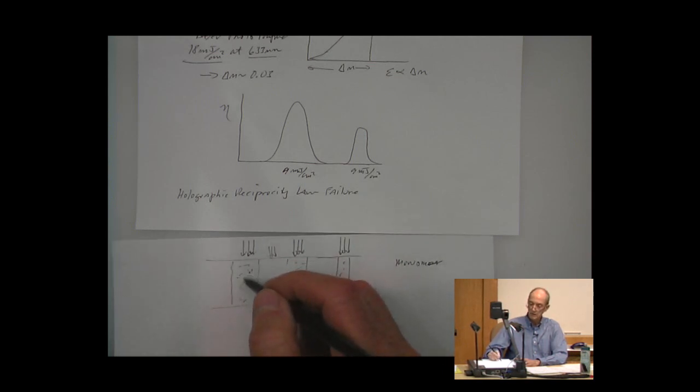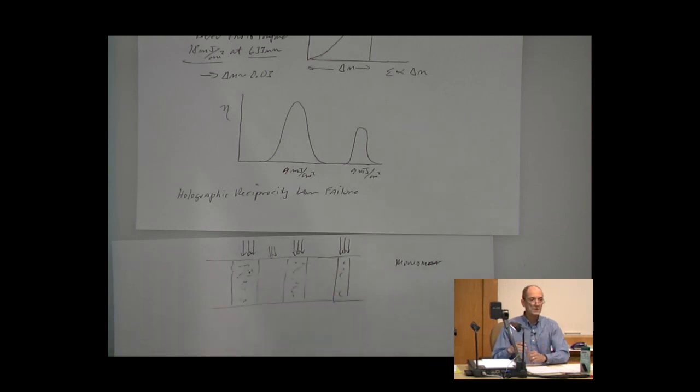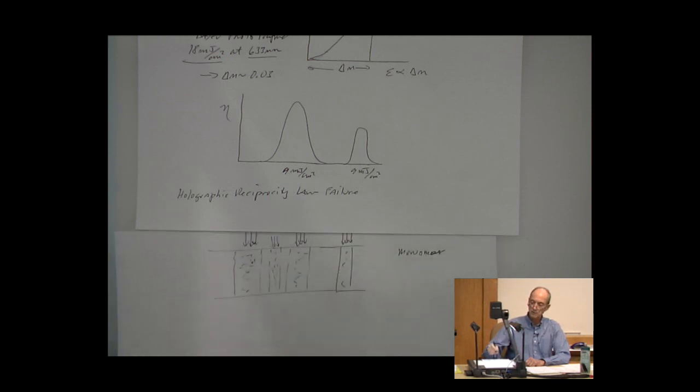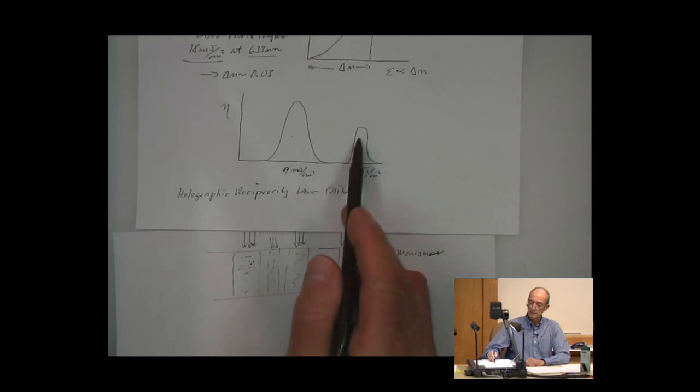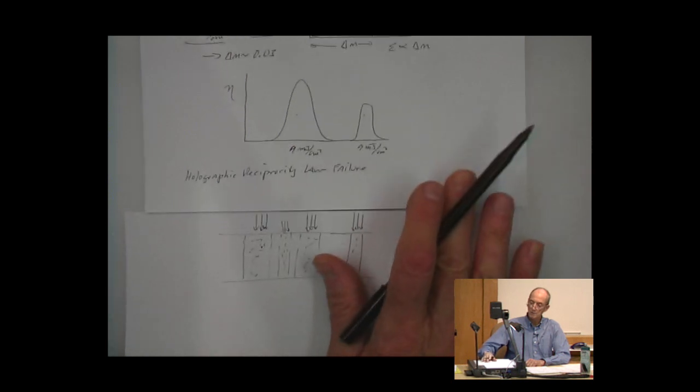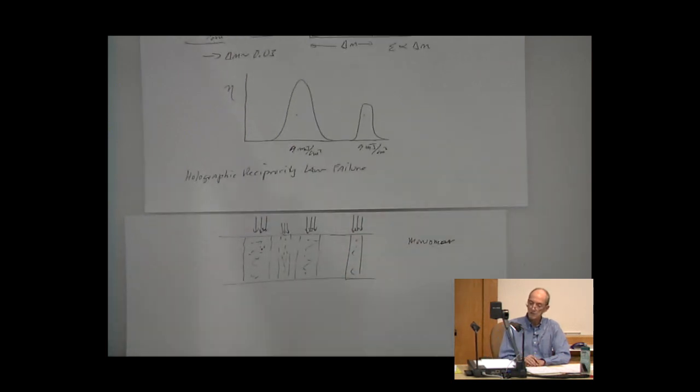So you're still illuminating these areas and polymerizing some additional monomer in those areas, and that would be lacking in the second hologram that was made. That gives rise to these non-equal diffraction efficiencies that you would get in the resulting hologram. So that's one thing that occurs in multiplexing.